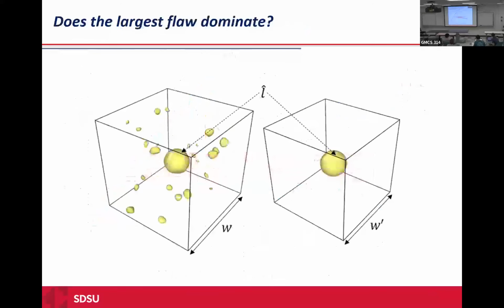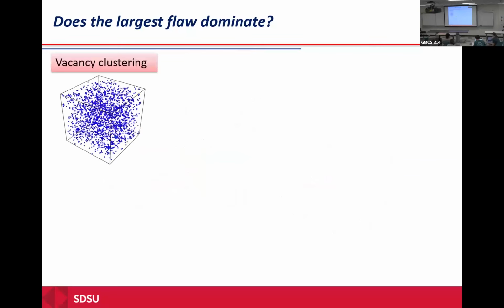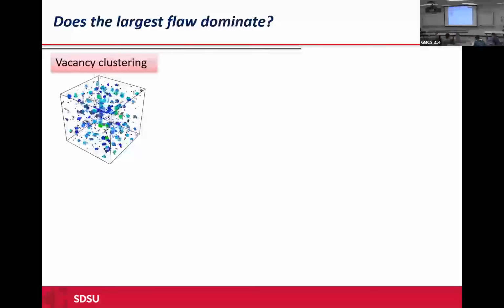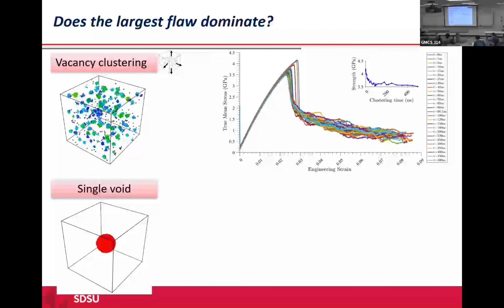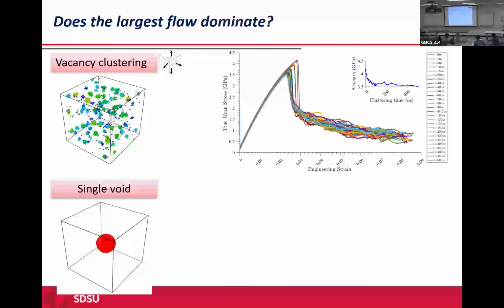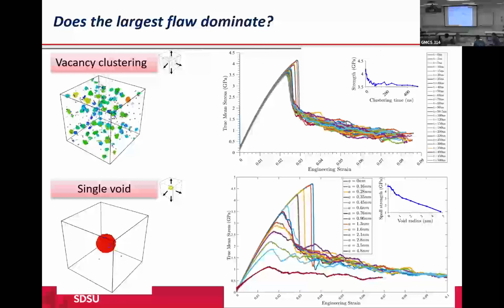This shows that by increasing the clustering time, we have a larger cluster size, which can decrease the strength of the material. Okay. We wanted to see if we can model this scenario with just a larger cluster size, having the larger cluster size without the distribution of the clusters, and predict the material behavior. Just to compare, we have a system with the distribution of vacancies and another one with just the larger cluster size. And we apply loading to both of them. This is the first one with the vacancy clustering, and the second one is just a single void with the same size as the larger cluster size.